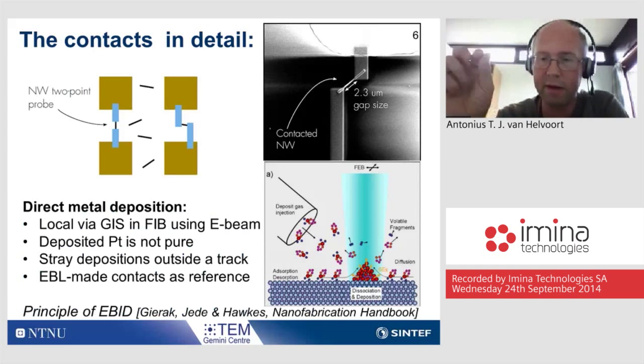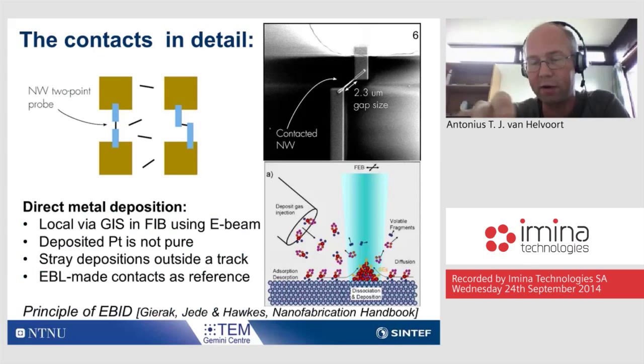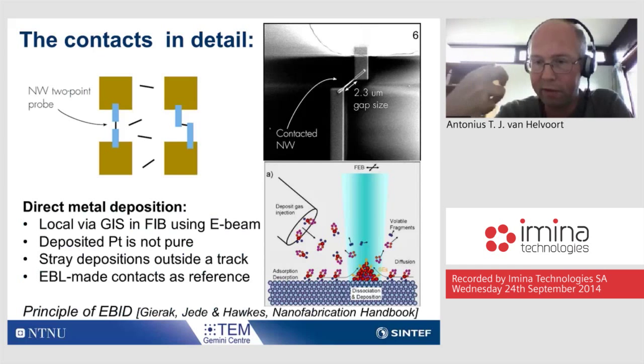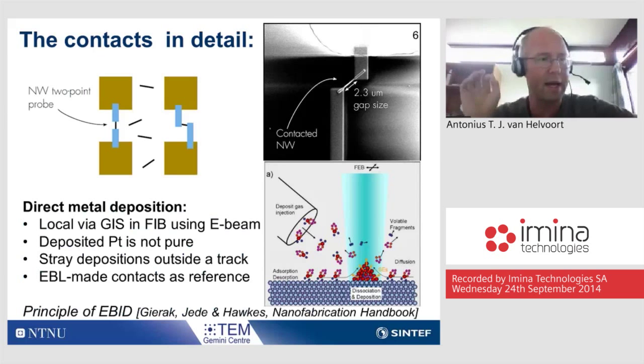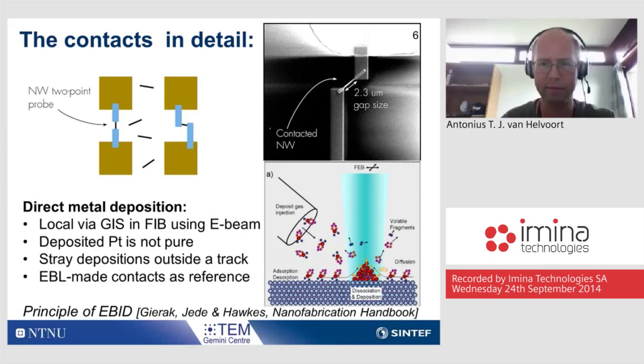For those who are not familiar with this deposition technique, what we do is we bring from the left, you can see there comes a needle, a nozzle in, which brings a precursor gas close to the surface, and the electron beam, here blue, which you can control in position, breaks up the molecules which come out, or actually it's the secondary electrons which break up these molecules. And the metal part, here shown in red, is deposited behind, and the other parts should fly off. If you now look closely at this deposition, it is not quite pure, and so there are some carbon remains in it.